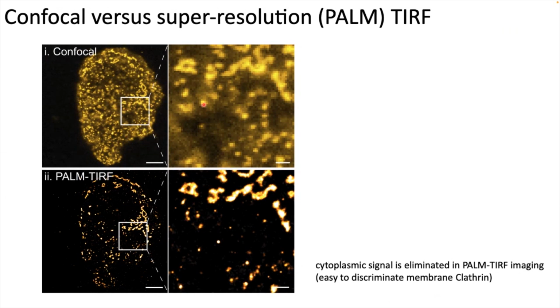And you can see two things. A, the resolution is better. So you can see here, for instance, these three dots, while here it just looks more like a line. So here you can clearly discriminate three spherical structures. But then you also see that there is much more background on the confocal image than on the PALM TIRF images. And that is not related to the super resolution per se.